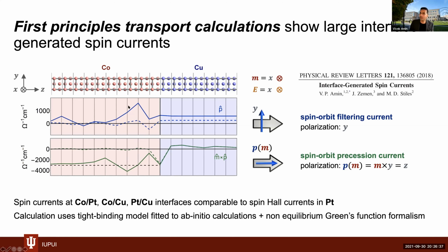If you look at this top effect, the spin-orbit filtering effect, you see that more or less these curves look kind of similar, right? It's off by a factor of 2 maybe, but you qualitatively get the same behavior. However, there's a drastic difference in the bottom plot when I turn on spin-orbit coupling or turn it off in the cobalt layer. If I turn it on, I get a spin current that undergoes dephasing in the ferromagnet like expected, but then it approaches a non-zero value.